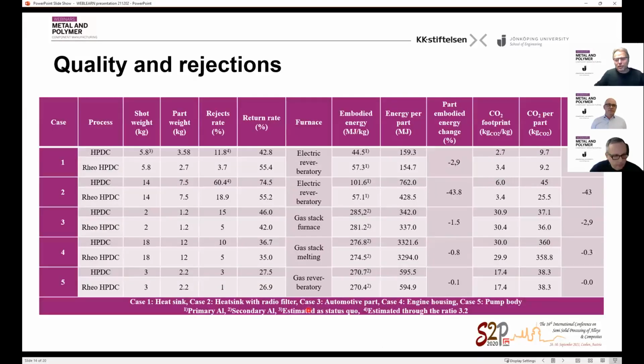Now, this is data that was presented during the S2P conference in Austria, where we talk about semi-solid casting. But that is not the focus here today. The important part here is that if you compare the shot weight with the part weight, you have a certain amount that is gating systems, and then you have your rejection rates, and that gives you a certain amount of material that is being returned. And this increases the oxide content of the material because you have gating systems, you have vent lines and things like that that go back into the melt. And you have material losses and you have accumulation of energy and carbon dioxide that will drive the climate impact of your foundry.